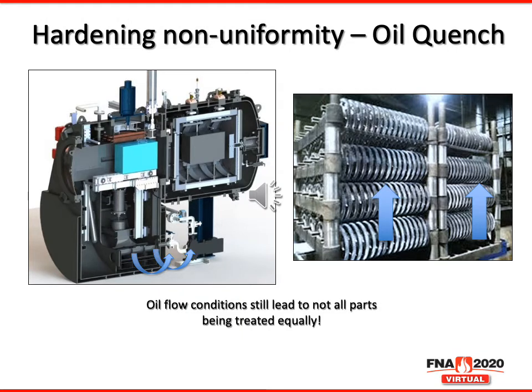To overcome this, you may think that, well, wouldn't it be better to switch to a liquid? That would improve the thermal conductivity of the media directly in contact with the part. Well, yes, it would. But in some cases, it may actually improve it too much. So we're still limited by the material and geometries that we're processing. Also, we don't fully eliminate the flow problem, because here, in this case, instead of the gas coming from around the outside of the load, the oil is being directed up through the middle of the load from bottom to top. So we still have a variation of temperature and velocity of the oil as it moves through the batch, meaning that not all parts in the batch see the same conditions.